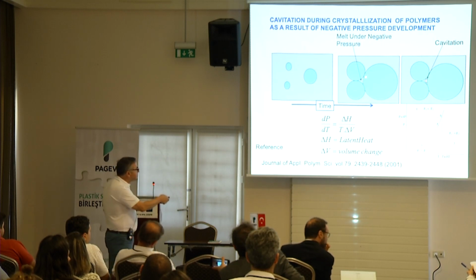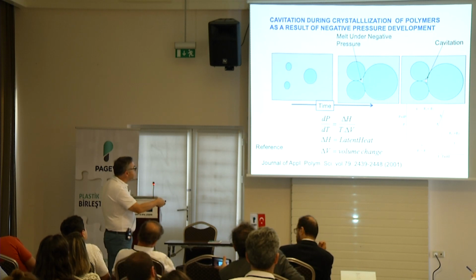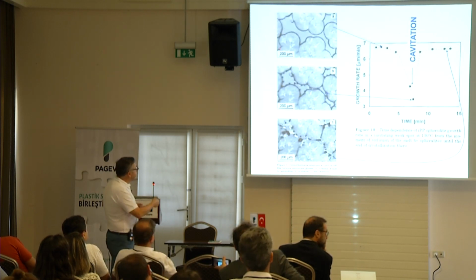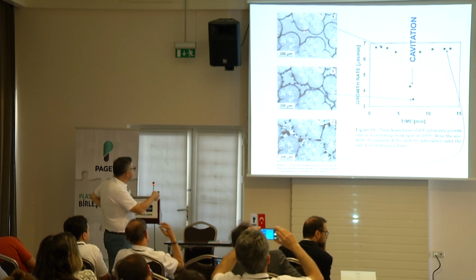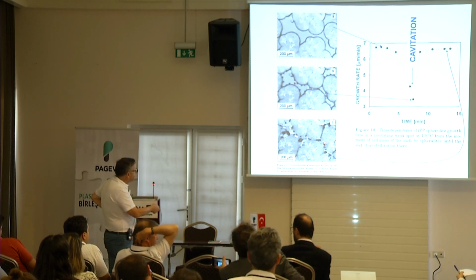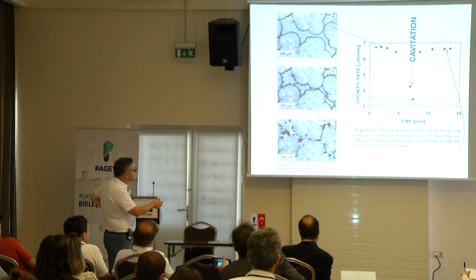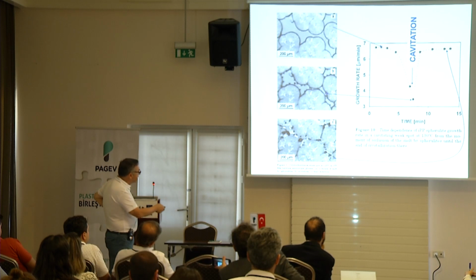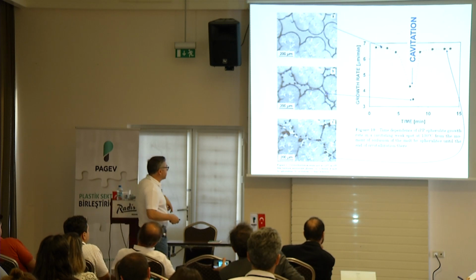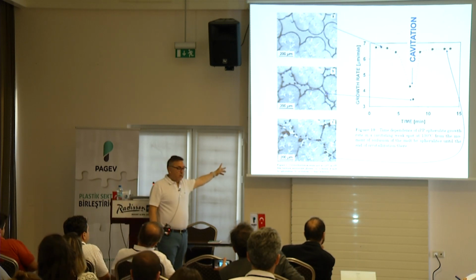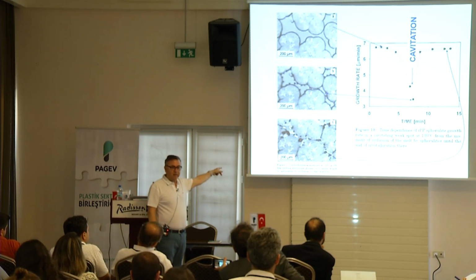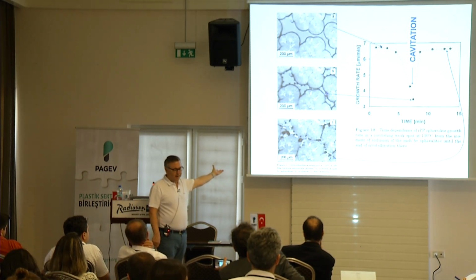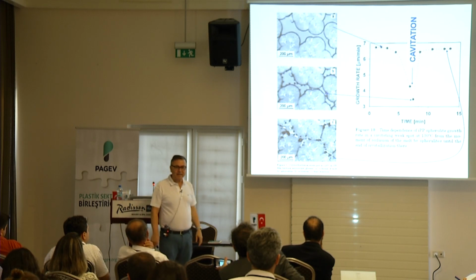It's because that portion is actually under negative pressure, and you can see it in equations and so on, but I'm not going to bother with that. So this is actually what happens. Here is the crystallization of isotactic polypropylene. They are approaching each other. You see the bubbles? They form and they form and they form. And as soon as that negative pressure occurs, people actually measure the growth rate drops dramatically because you no longer have the material to feed the hungry crystallization process. But look at it. What kind of property is going to be influenced by this? Impact? Yeah.